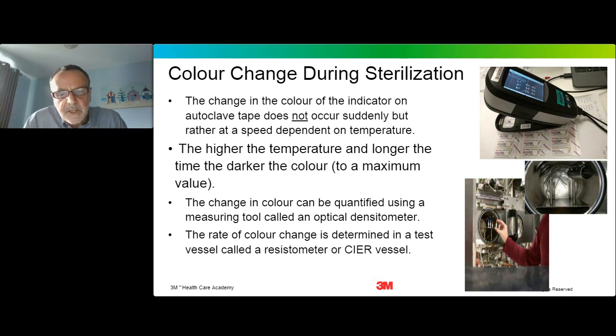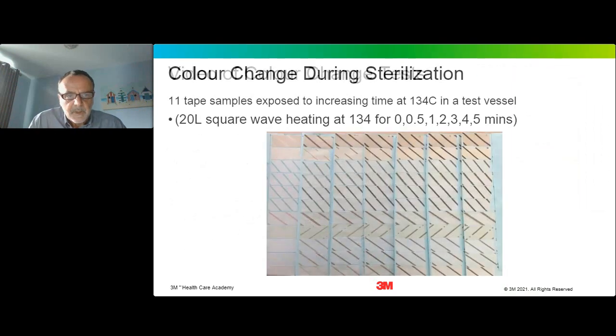Now, obviously, normally these autoclave tapes are judged by visual observation, but you can also measure the colour and quantify the colour using a reflectance densitometer or spectrophotometer, which you can see in the top right-hand corner of the slide here. And this is actually measuring the extent of colour change which has taken place.